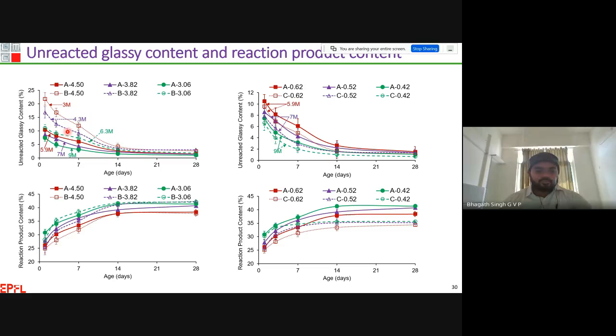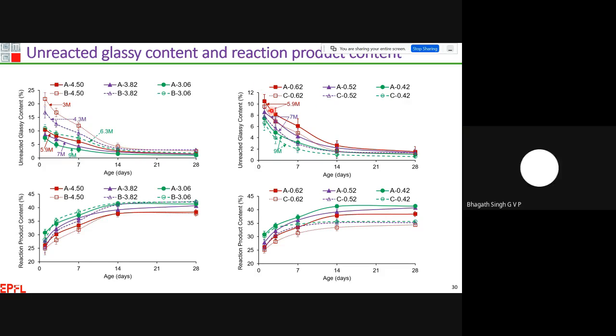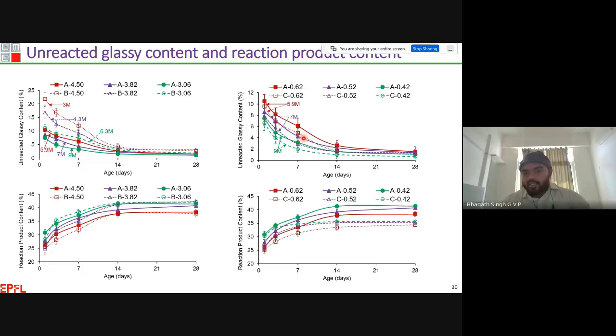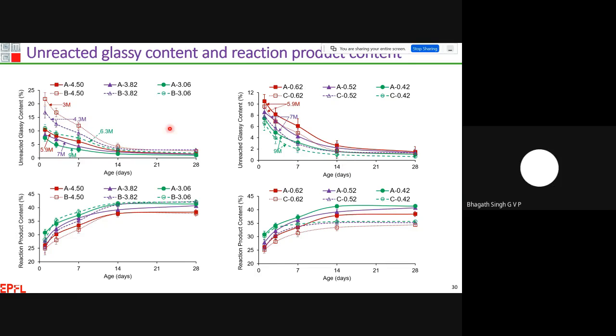As you can see here, the total reactive oxide ratio mixes are almost dissolved by 14 days, and thereby there is not much difference from 14 to 28 days. Most of the fly ash is dissolved by 7 days. But in the case of working solution ratios, you can see a slow decrease in the unreacted glassy content, and more or less both results are similar. The only thing is that when we maintain the total reactive oxide ratios, we have higher silicates and the molarity is also high compared to 3 molar. That is the reason we can achieve higher compressive strength in the case of total reactive oxide ratio mixes.